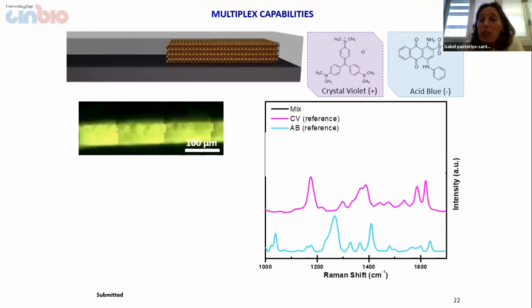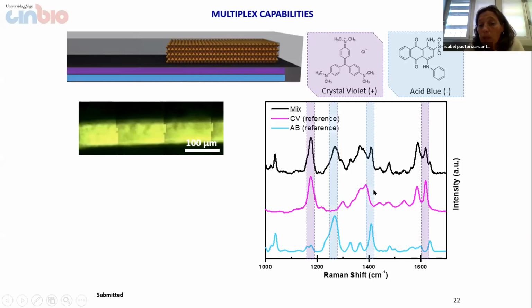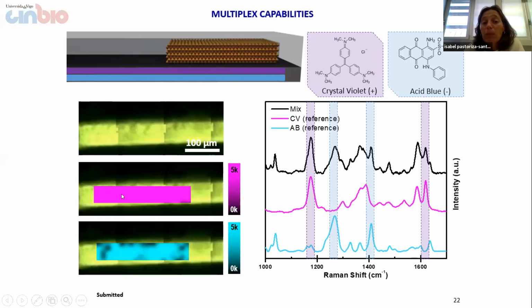The next step was to check the multiplex capabilities, to check if we are able to detect more than one molecule at the same time. In that case, we have used as model molecules crystal violet and acid blue. Each molecule presents a specific Raman signature. If we mix and inject in our microfluidic chip, and we analyze by SERS, what we observe is that in the resulting SERS spectra, we observe signals from crystal violet and also signals from acid blue. And even in the SERS intensity map, we observe that both molecules are homogeneously distributed.